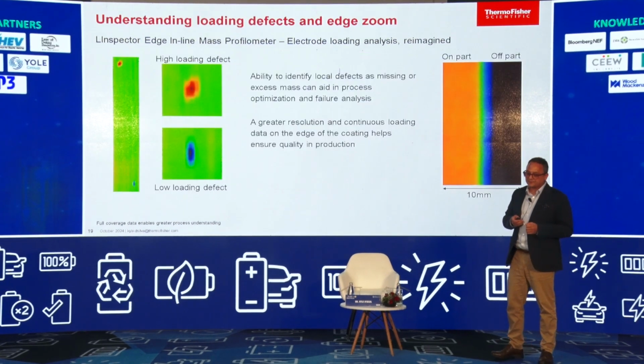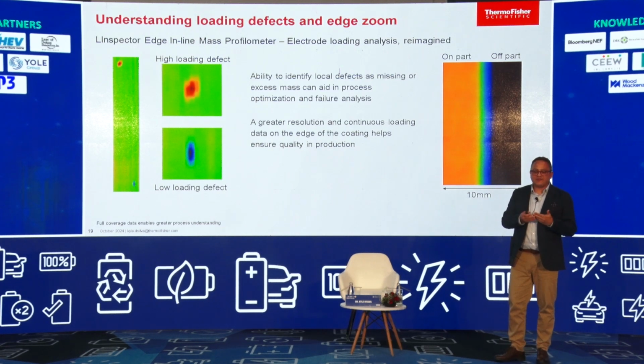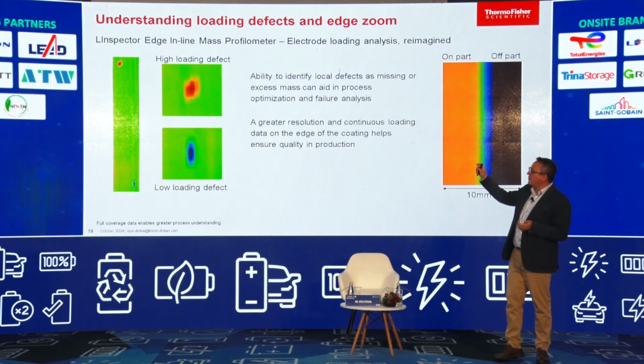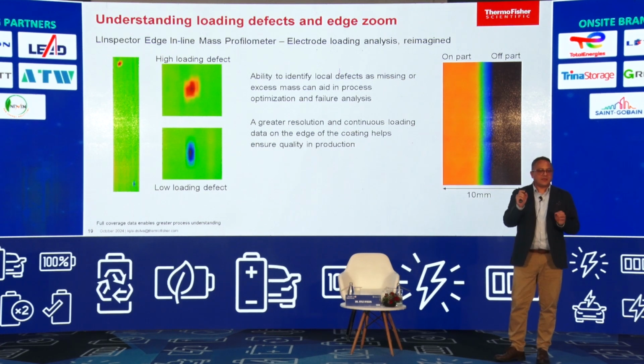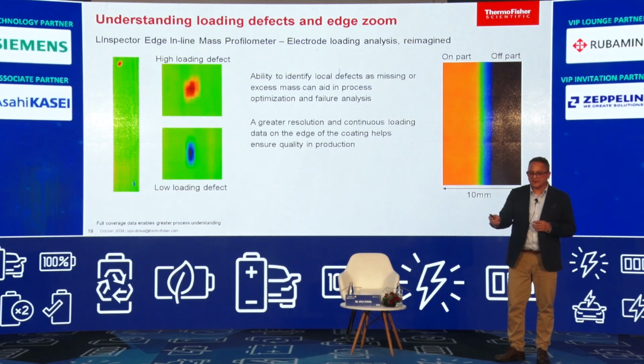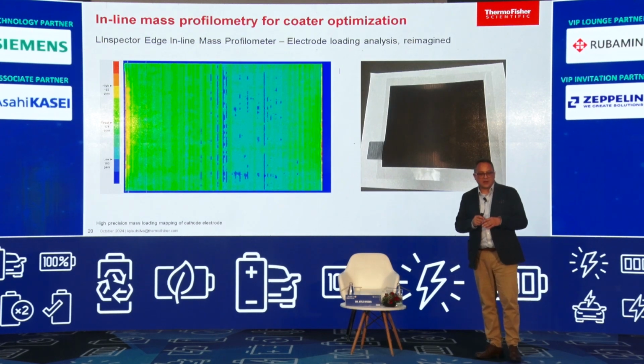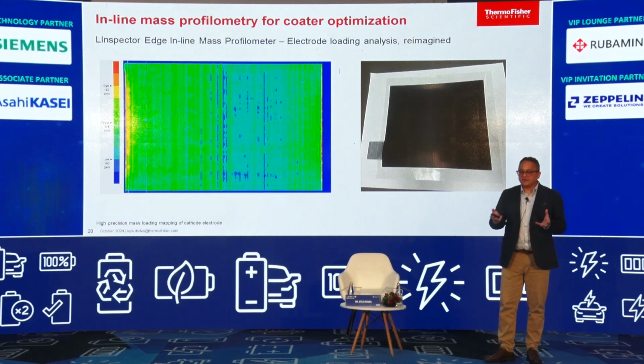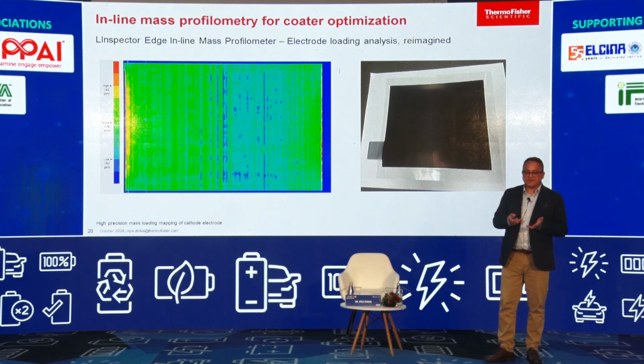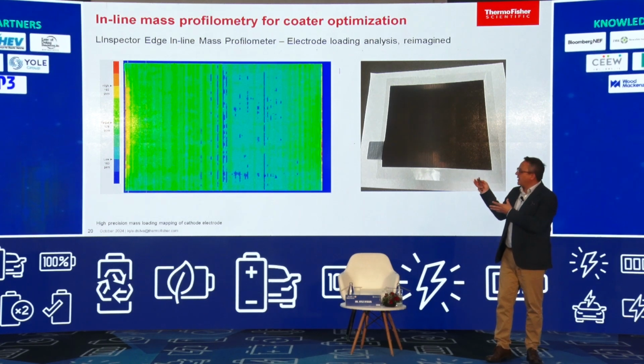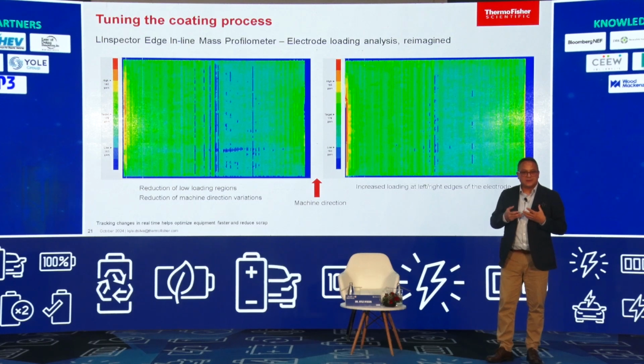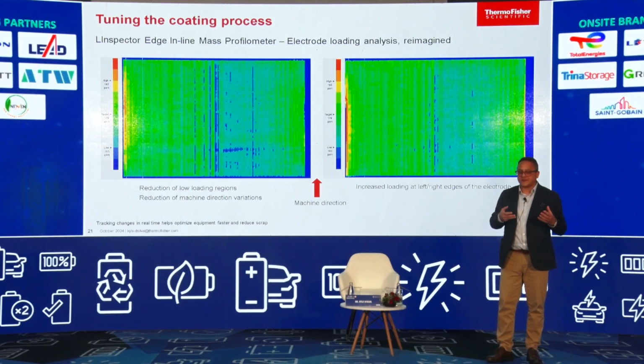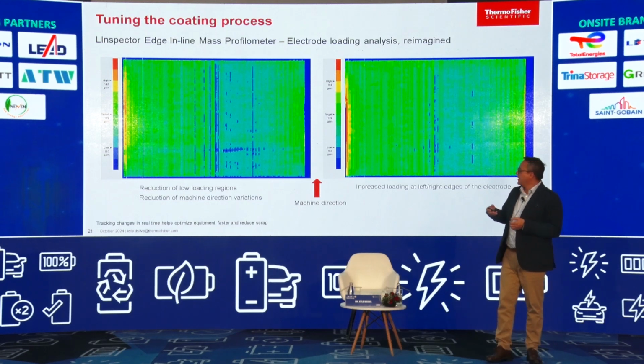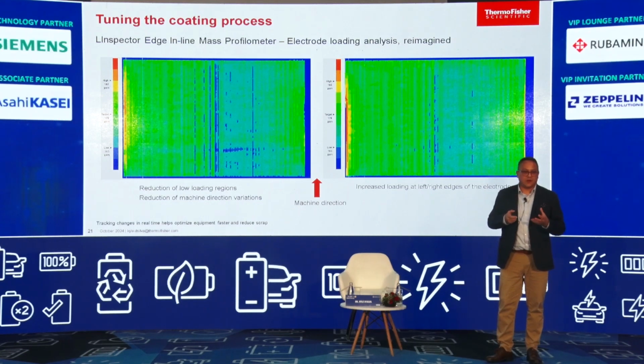So here you can really see quite high definition of very, very small defects, high loading and low loading or scratches. And you can see that we get great resolution at the edges of the patches. So here's an example of a real patch battery where you can see that there are some ripples and there are some coating defects. The idea is that you can make adjustments on the fly. Once you find a strip that is out of tolerance, such as the one on the left-hand side, you can adjust the flow parameters of your slot die during the process to reduce the number of defects or non-compliances.